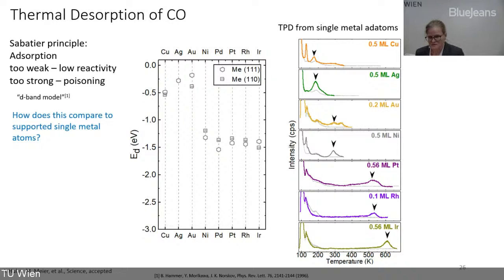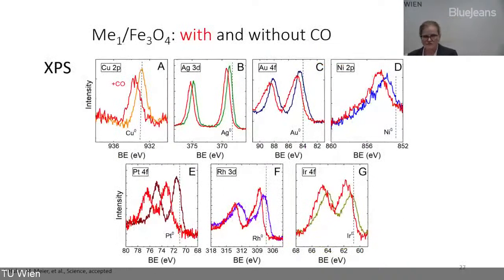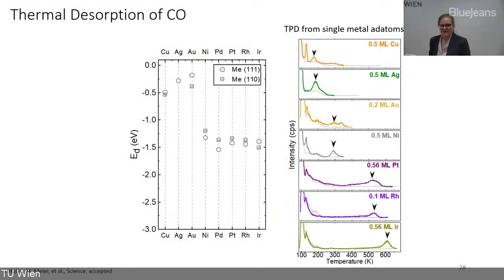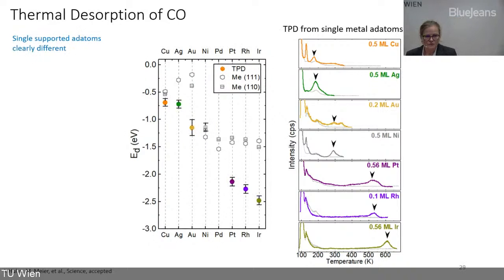The expert might ask, how do we know? We always combine different experiments. For example, XPS, we can clearly see how the XPS peak shifts. And then from these desorption temperatures, we were able to convert this into desorption energies and plot them together with what's known for this metal single crystal.